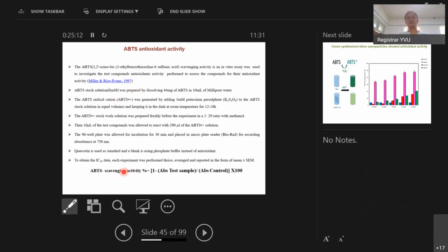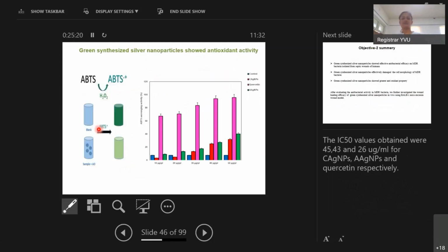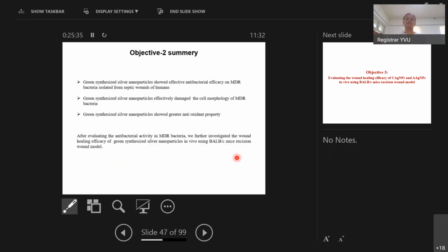This is the general protocol, and this is the principle used for assessing the antioxidant activity. The light blue color solution turns into a dark green solution. This graphical representation shows the IC50 values of CAGNPs 45 and AAGNPs 43 and quercetin 26 micrograms per ml. Coming to my objective 2, green synthesized silver nanoparticles showed effective antibacterial efficacy against multi-drug resistant bacteria isolated from septic wounds of humans. And these green synthesized silver nanoparticles effectively damage cellular morphology in MDR bacteria, and showed greater antioxidant property.